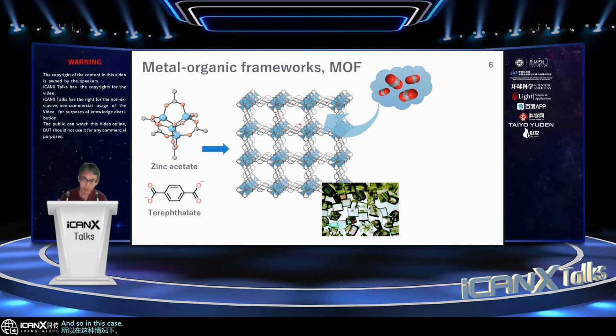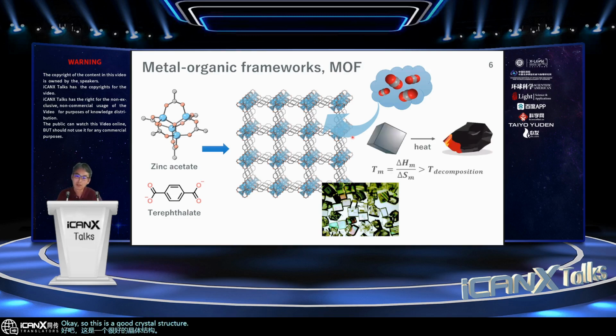In this case, we can clearly see the 1 or 2 nanometer pore structure inside this crystal structure. So we can make use of this pore to capture small gas molecules or ions and so on. This is a good crystal structure, but when we think about whether this type of structure may form a melt state by heating, or a glassy state by some treatment, it has been impossible. Only crystal structures existed, because after making crystals, usually organic polymers, ceramics, and metals will form a melt state by heating, right?